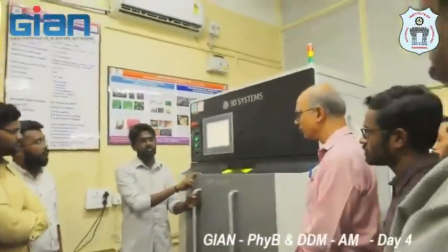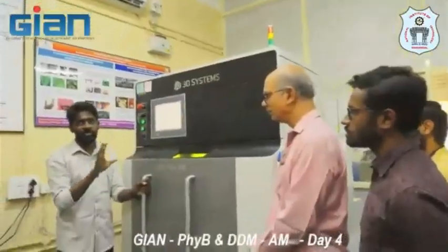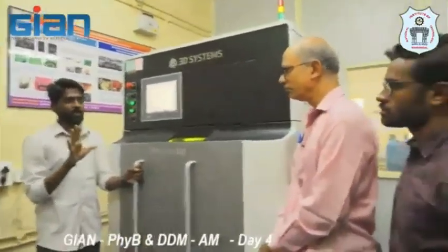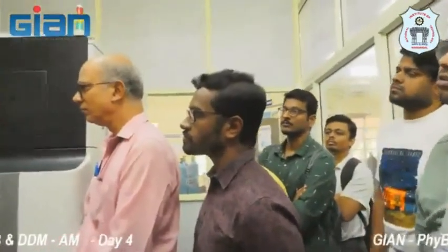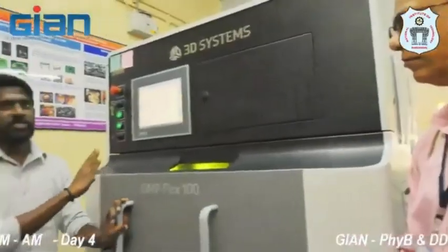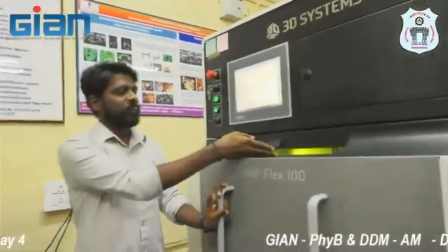Layer thickness you can't change because right now we are following only 30 micron layer thickness. Hatch thickness and hatch spacing you can change, around 75 microns like that. In this machine we can make four materials: aluminium, titanium, cobalt chromium, followed by stainless steel. Right now we are printing stainless steel, 17-4 PH grade, precipitation hardening steel.